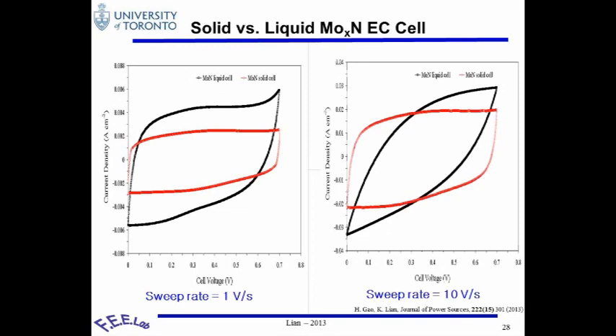However, when you have a higher cycle rate, up to 10 volts per second, the liquid capacitor looks much more tilted due to the high resistance. However, the solid state capacitor stays in the capacitive stage.